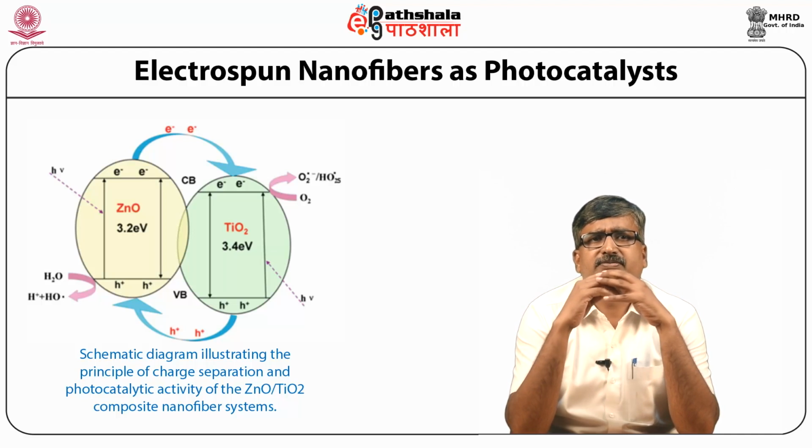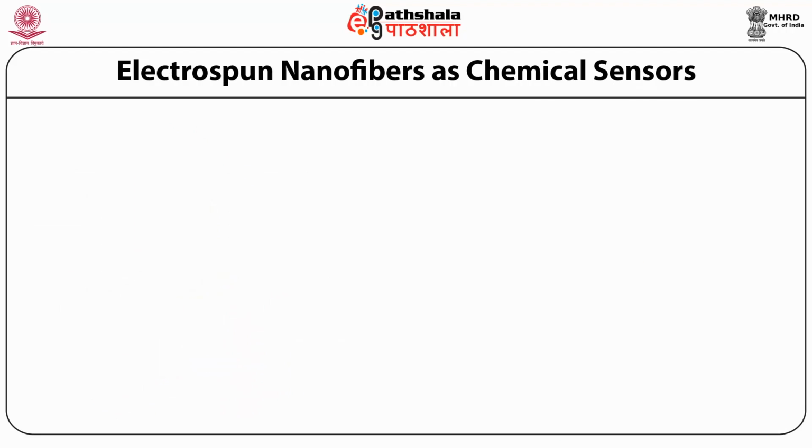It has been observed that the optimal photocatalytic activity of silver ZnO nanofibril could exceed that of pure ZnO nanofibers by a factor of more than 25, and the photocatalytic activity of the composite can be tuned by adjusting the silver content.